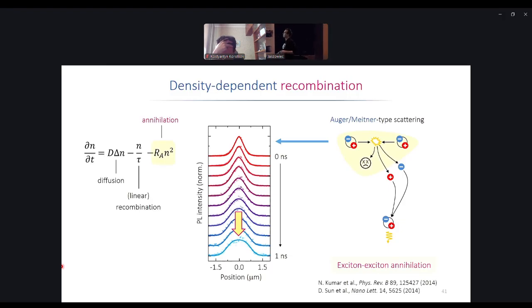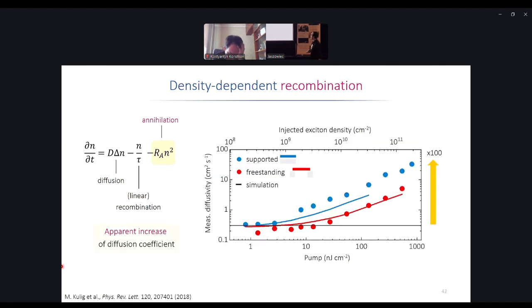If one wants to model it, this is one way to do it, to add an annihilation term in addition to the linear recombination. Yeah? And in fact, as you see on this reference, this is something that is known also for bulk materials. So this is an example for cuprous oxide where this process takes place and where exactly this effect can be observed. In this particular case, one can also make some quantitative estimation of how it should be for the measurement.